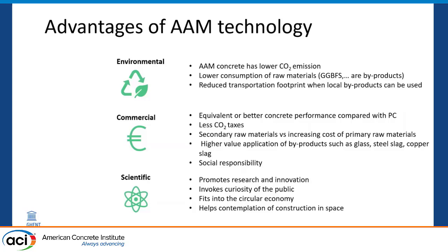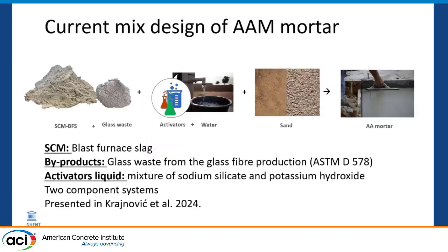helps contemplation of construction. So for my current mix design for the supplementary cementitious material, I used blast furnace slag, which is locally available in Ghent. We used glass waste powder from glass fiber production from Owens Corning company. We activated it with a mixture of sodium silicate and potassium hydroxide, and with sand to create a two-component system, alkali-activated mortar. This mix design is presented in detail in our recent publication.